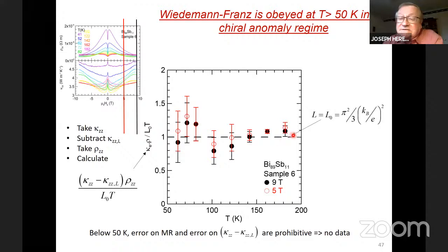You have to verify that you have a constant Lorentz ratio, which, you know, are the points horizontal? Well, yes. And you verify whether or not the constant is equal to the free electron value of pi squared over 3 k over e squared. And I think this plot tells you that the answer is yes. Now we have to cut the sample at 50 Kelvin for the errors that I explained. Below 50 Kelvin, we have a prohibitive error on the difference between electronic and lattice thermal conductivity. And of course, we also have a steadily increasing error on the resistivity because the geometrical magneto resistance shows up as well. So the error bars become of the same magnitude as the measurements if we go below 50 Kelvin, and this becomes meaningless.